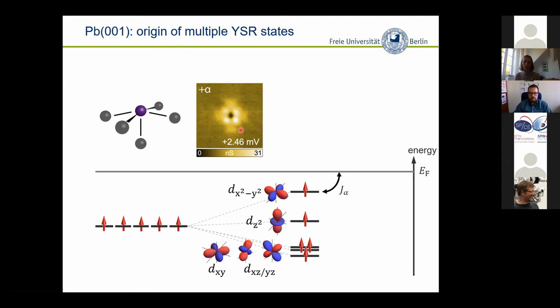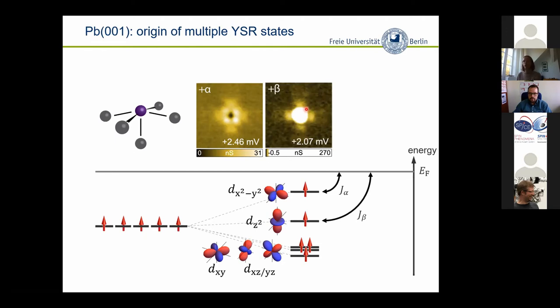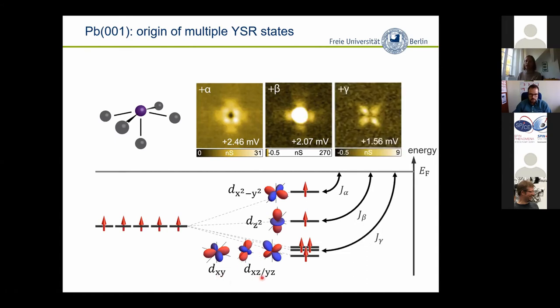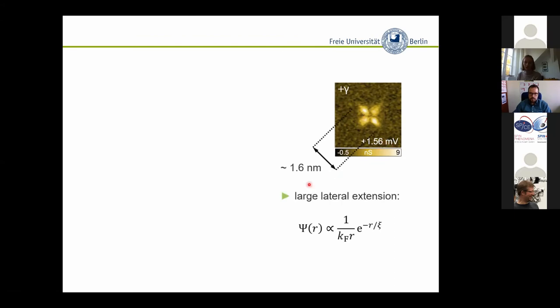Often the magnetic exchange scattering potential is treated as point-like, but in these real systems you should be more careful — the Shiba states inherit the symmetry of the scattering potential. What you need to look at is conservation of energy and angular momentum, and here we are in the L=2 shell. From the top with an STM, this looks like the d(x²-y²) orbital. The d(z²) is the one protruding most toward the STM tip so it has the largest intensity. In the plane, we see the d(xy), d(xz), d(yz) orbitals with their clover shape. The extent is much larger than the d orbital itself because the substrate electrons scatter and feel the symmetry on a much larger spatial scale.